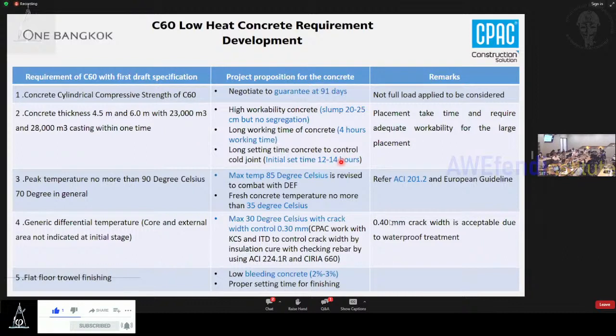This is a table that summarizes what we talked about for the concrete properties of the project. First of all, as I mentioned, we talked about C60 for the mat foundation, but in general we have to use high volume fly ash. So in general, we guarantee the compressive strength at 28 days, but for this one, to achieve C60 at 28 days, I think it's impossible. So we talked about a 91 day strength guarantee from the concrete supplier. This doesn't matter for the construction sequence because the concrete can develop the strength. Once at 28 days, it's around 60%, so many workers can continue their job. It doesn't have any effect from this.